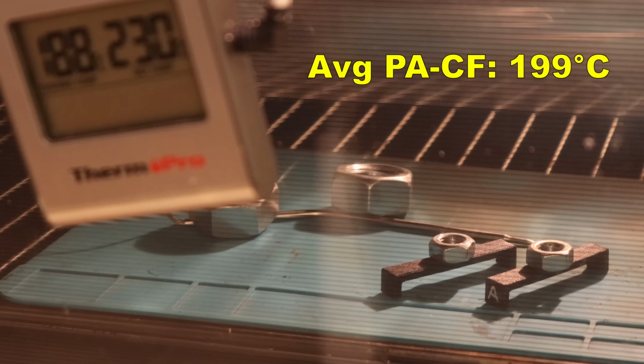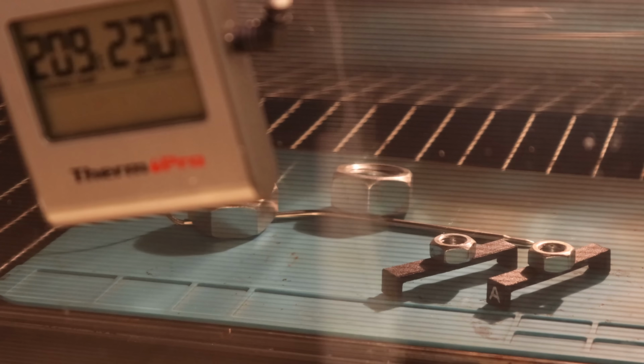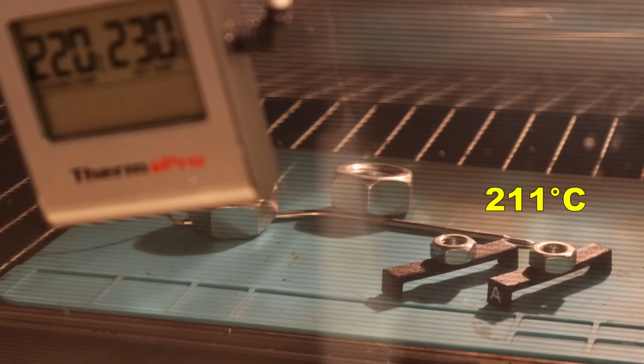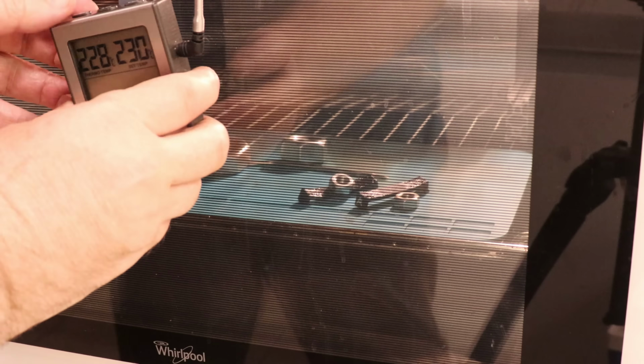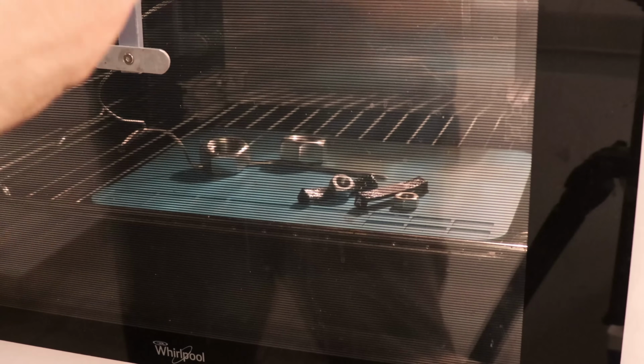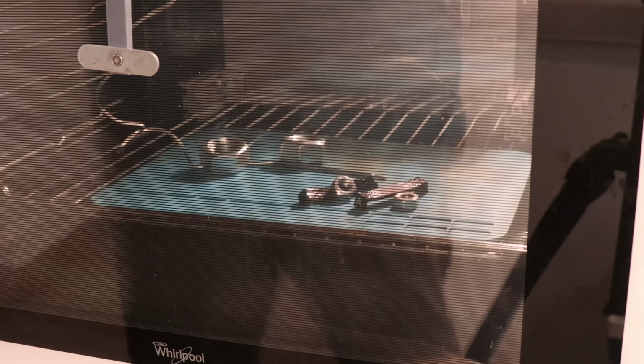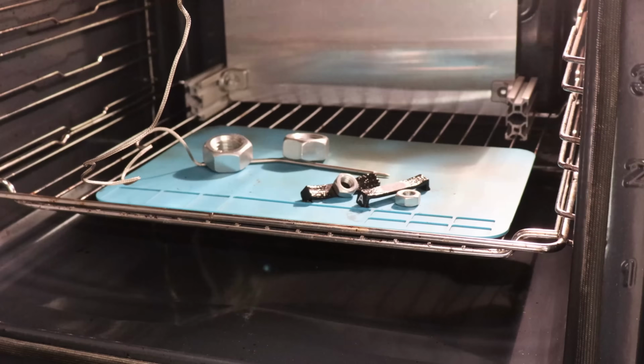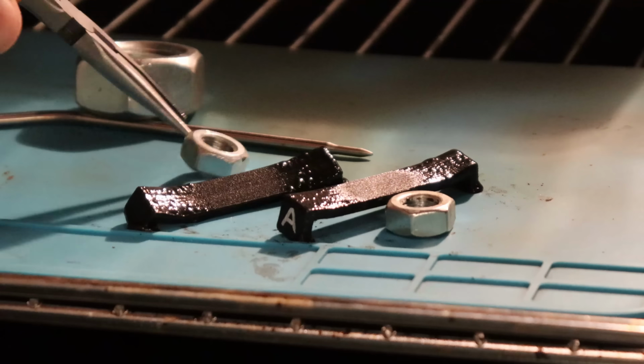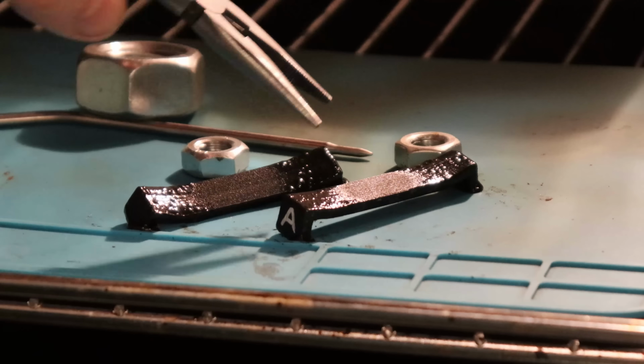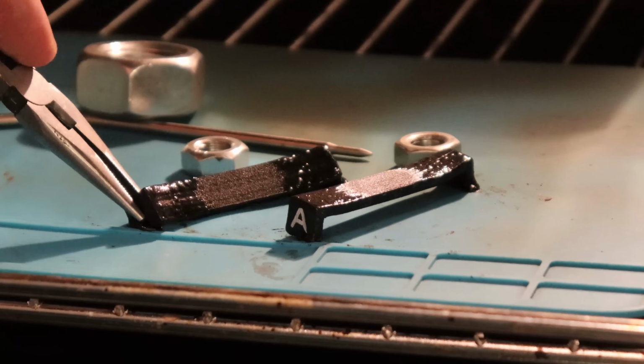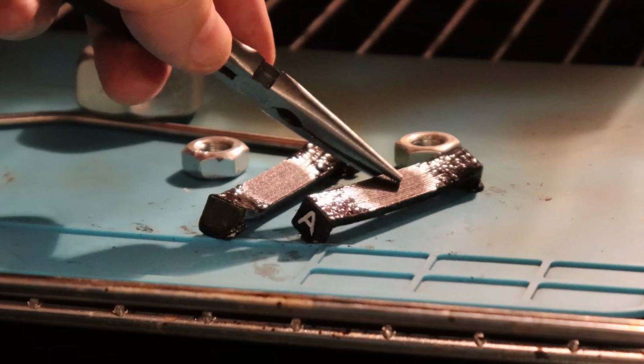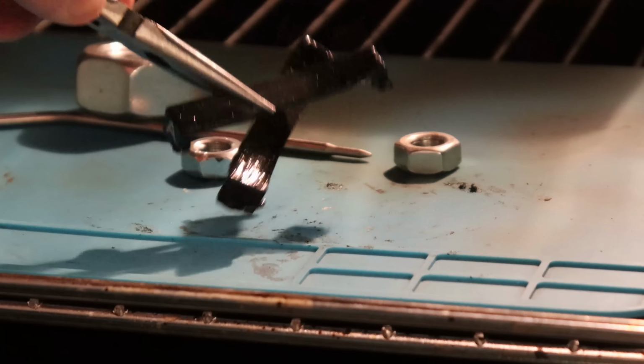The average PACF starts to deform at 199 degrees Celsius, and this one at 211, but it starts to deform quite suddenly, even the surface changes. So the real practical usage temperature is lower than this, but this is what I can measure, and this will be recorded in the summary table for my Patreon supporters. It is quite soft at this temperature now.